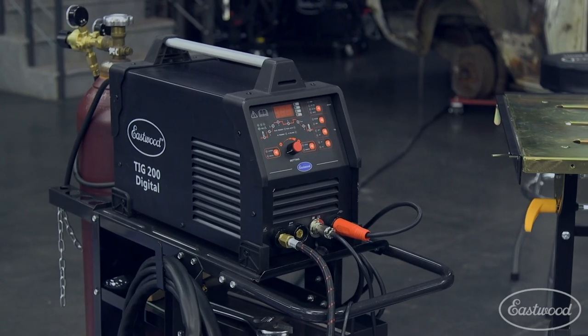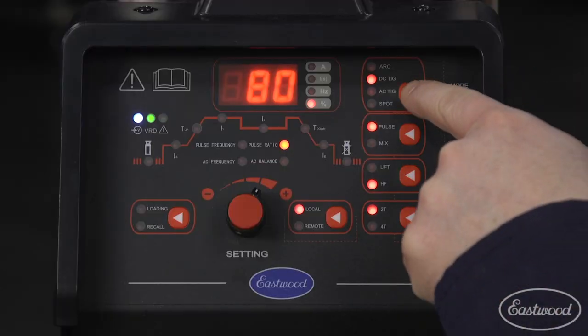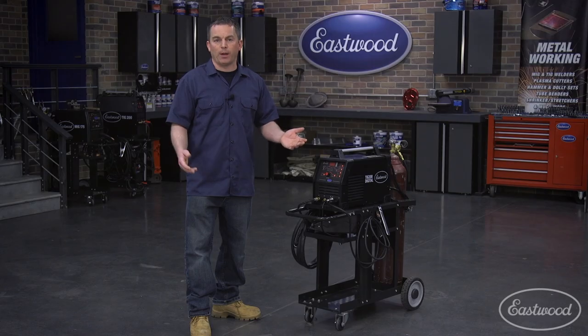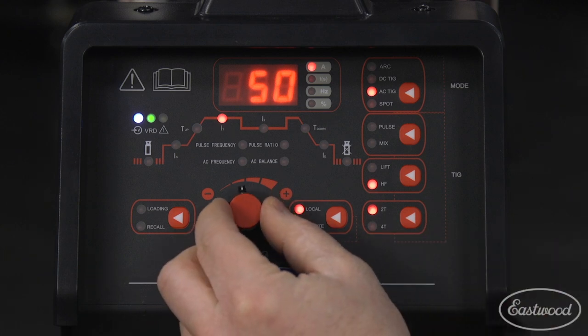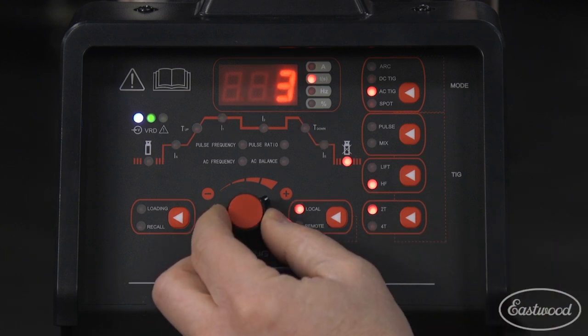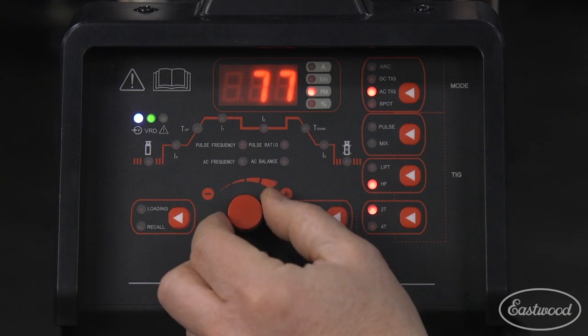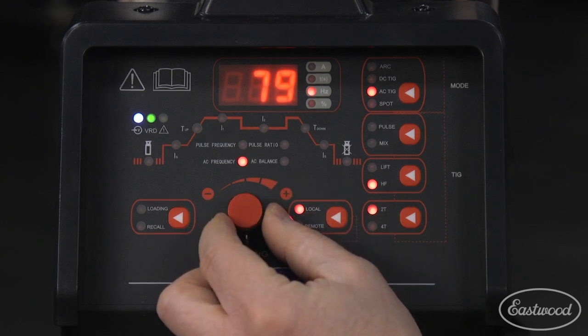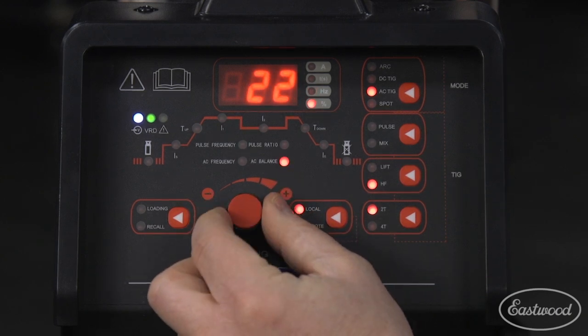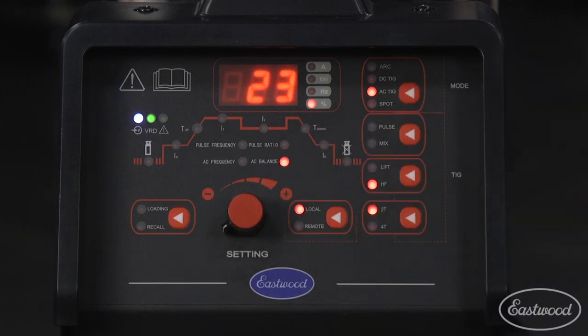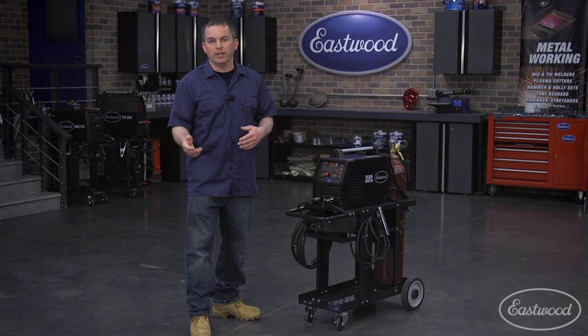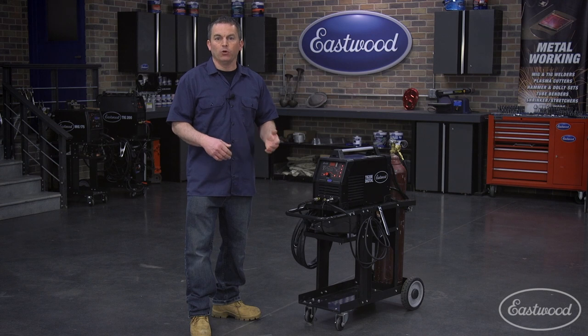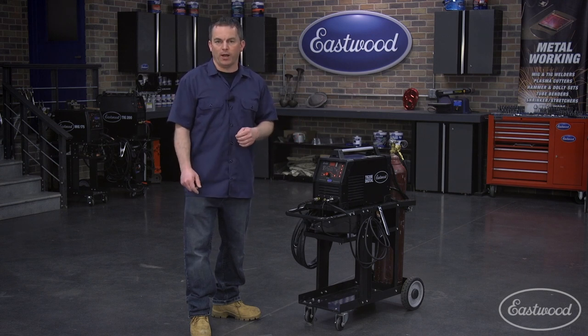To set the AC pulse for welding aluminum, select AC TIG, then select all of your other parameters like you did for DC TIG welding. In AC mode, you'll also have the ability to set AC frequency and AC balance. Basically, this is going to allow you to control the arc shape, penetration, and cleaning. Higher frequency means a tighter weld bead, and lower frequency means a wider weld bead. You'll get good penetration whether it's set high or low, as long as you're using the proper amperage.